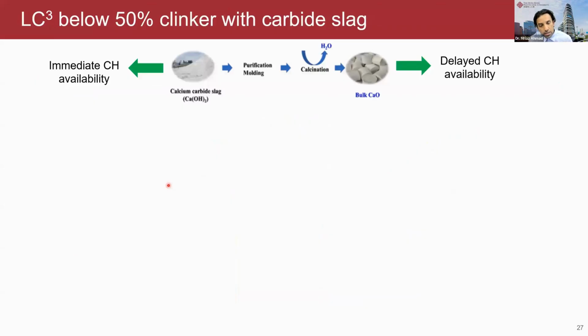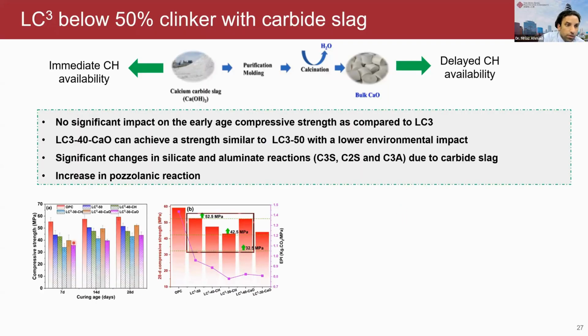And in the next approach, we again created LC cube mixes with only 40 and 30% clinker content. And we tested with these two sources of carbide slag. One is just a raw carbide slag, which has a lot of calcium hydroxide. The other one, we tried to calcine this calcium carbide slag to produce quicklime or calcium oxide. The major idea was that this calcium oxide has very high heat during the early reaction, and it may boost the early age compressive strength. So again, these are the results.